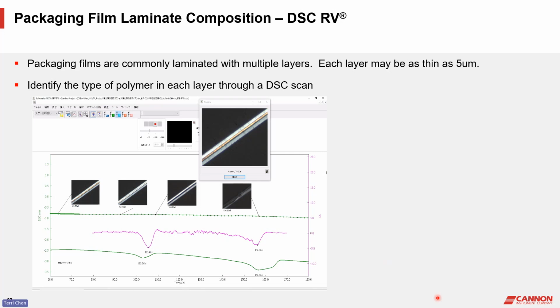With this question in mind, we reran this sample under the microscope. From this video, we can see that when the temperature is approaching the melting temperature of PE, the center layer first turns black. This tells us that this center layer is made of polyethylene.